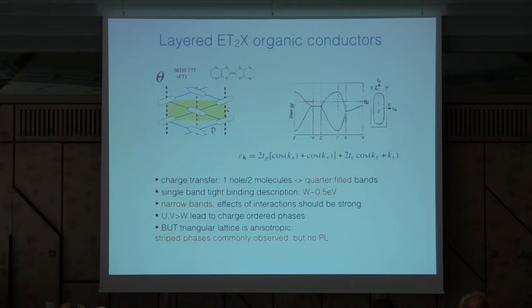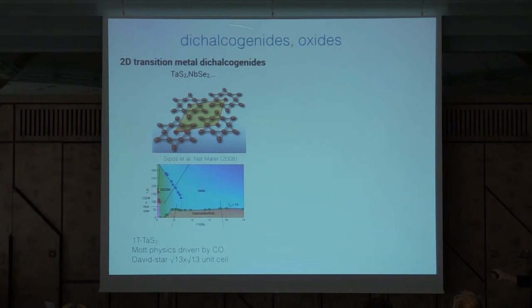The bandwidths are quite narrow, so you can expect Coulomb interactions to be really important there. And in fact, charge-ordered phases are very often observed, but unfortunately, they have this striped shape. So the threefold pinball liquid is not observed in these systems. If we really want to find this pinball phase, we have to go to other systems. One idea is the dichalcogenide family. There's one very interesting example, which is 1T-TaS2.